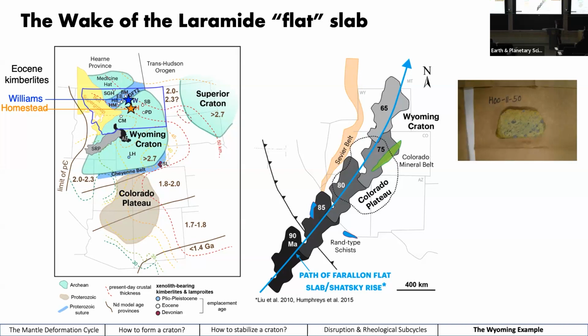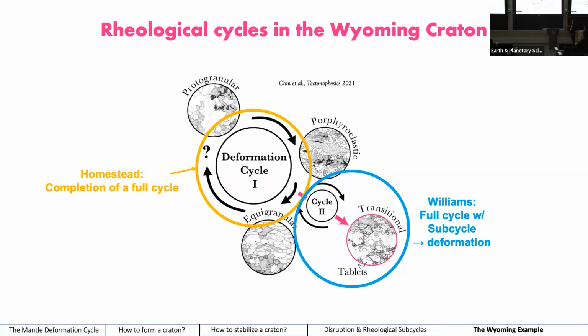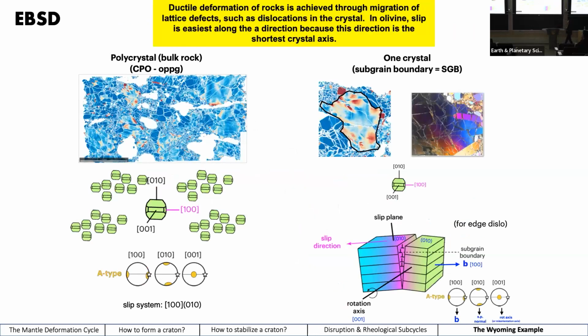So it's important to remember that these kimberlites erupted just as we think this slab was maybe reaching into it. Within the Wyoming craton, we're focusing on these two areas because they have abundant xenoliths. Within the Homestead kimberlite, we observed predominantly protogranular and equigranular textures with very few deformed porphyroclastic ones. So we thought maybe whatever mantle the kimberlite at Homestead sampled, it's sort of a completion of the cycle. We didn't see any of these transitional textures. But at Williams, we saw many samples that had these tablet olivines. That's kind of interesting, and we'll talk about an idea for why. Okay, so I should have shown this earlier, but this is what we use for EBSD data.